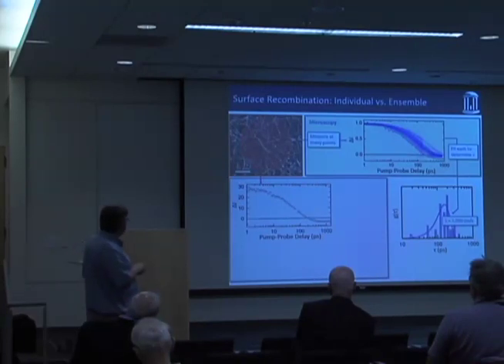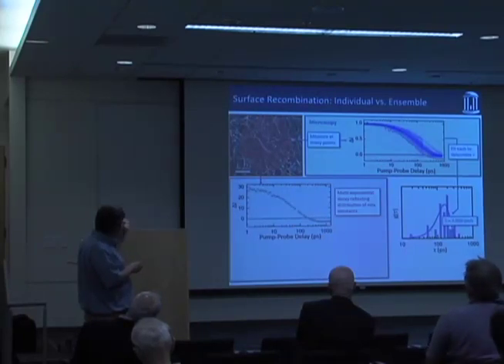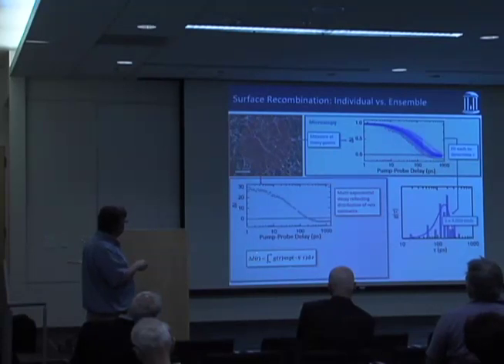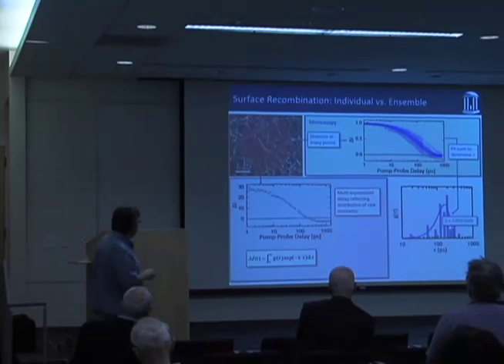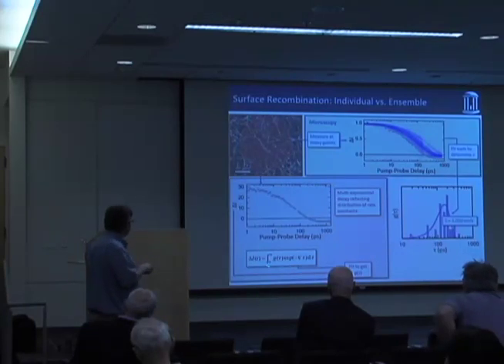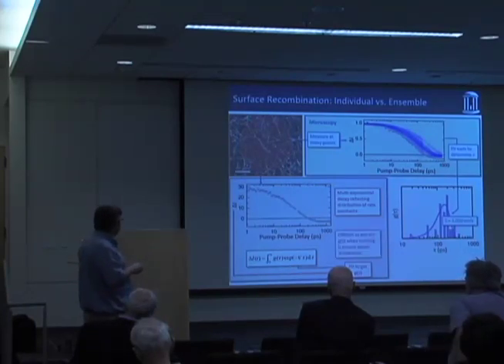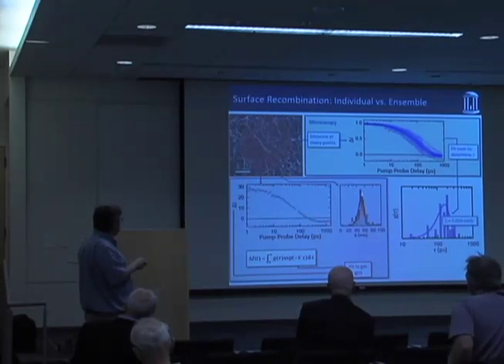But we thought, well, could we actually pull out a distribution? Because this decay is multi-exponential, you could fit that decay in this sort of way, where you have a distribution of lifetimes weighting all these single exponentials. And then I could take that and fit it to get this distribution. But if you've ever done anything like this, you know that those fits are highly unstable and they never really work unless you know something about that distribution. But we do know something about that distribution because I can measure the diameters.